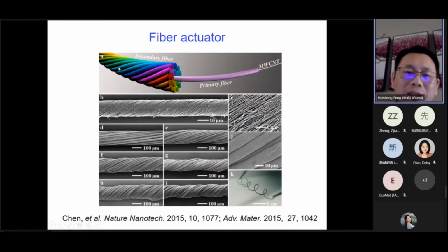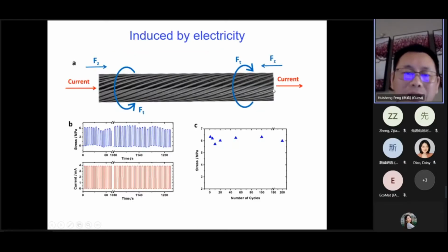Also interesting, because this material is also conductive. For this fiber material, when we pass an electric current, very interestingly, the fiber will show two interesting actuations. First, it will rotate, and the carbon nanotubes are aligned in this way, and here is the helix direction. During this process, the helix angle will become higher, and the fiber will become tighter, and also there is a shrinking along the length direction. So there are two actuations, and it's highly reversible.